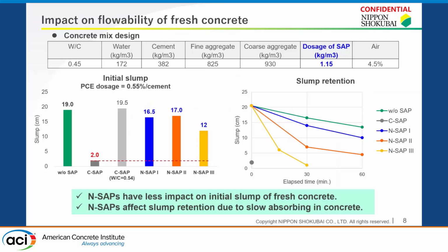This slide highlights the impact of SAP on flowability of fresh concrete. In our concrete test mix design, the water cement ratio was 0.45, and we used 1.15 kg of SAP per cubic meter of concrete. We compared initial slump at the same dosage of PCE.